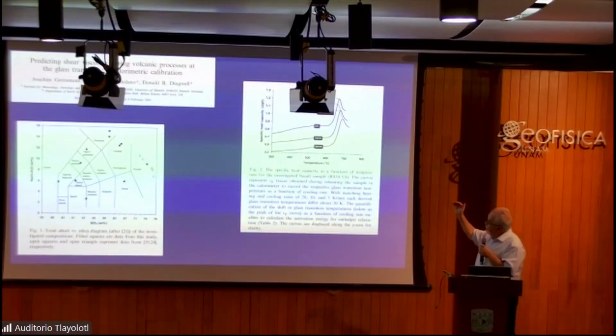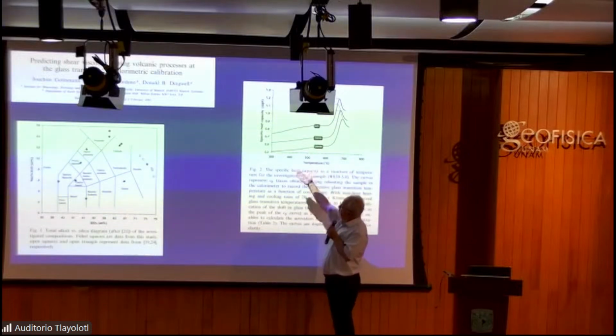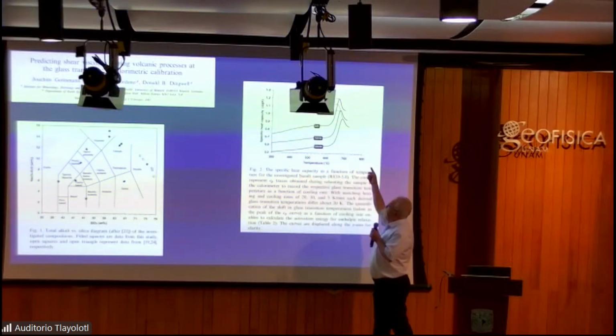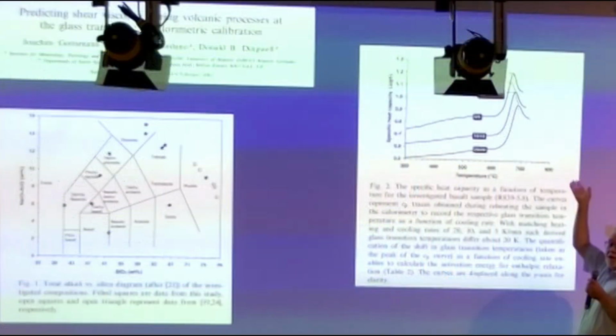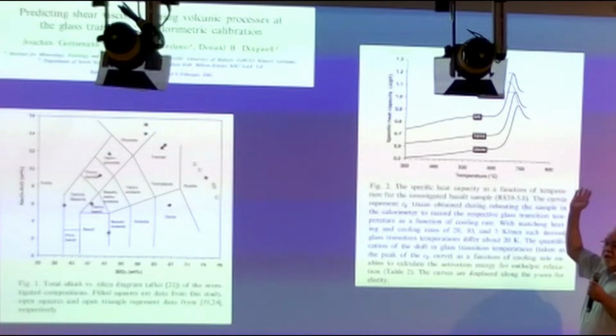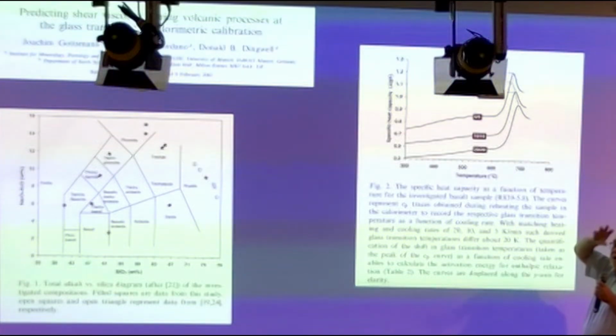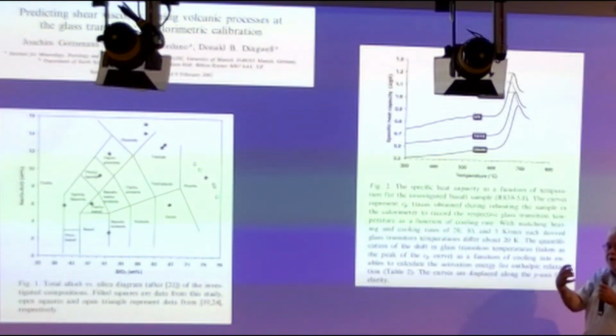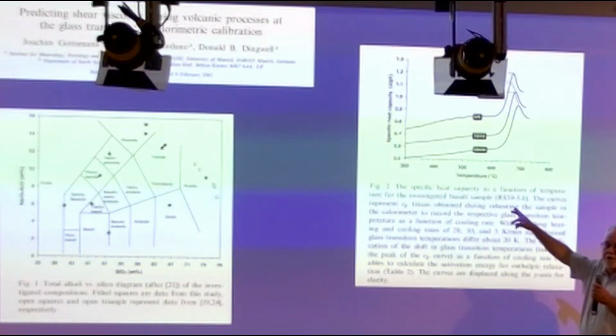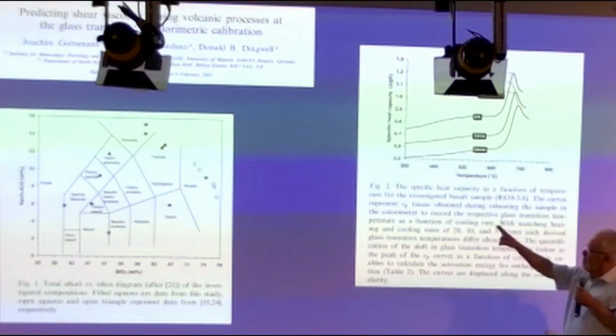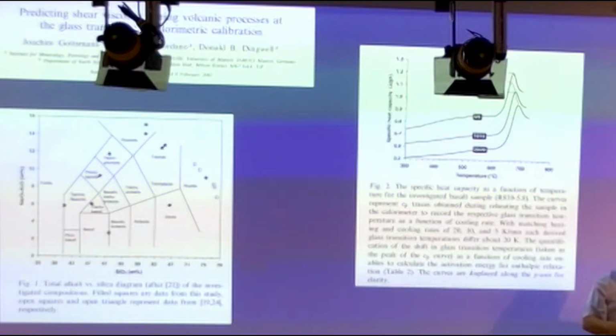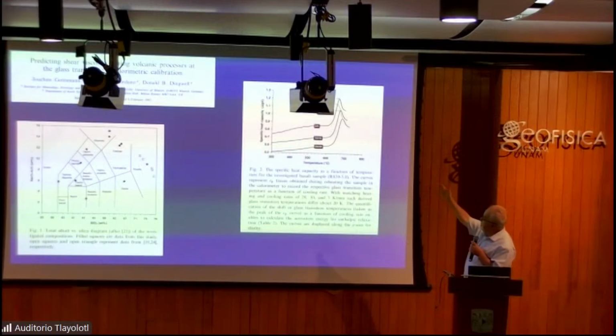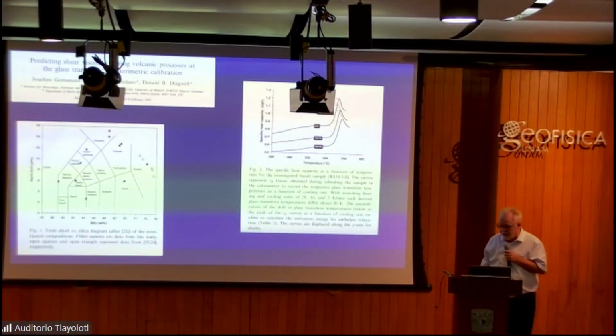And you have on the left-hand side a heat capacity which is relatively low at low temperature, and you have on the right-hand side the hint that the heat capacity is going to be much higher. And the reason it's much higher is because you have the liquid structure changing through configuration as it goes up in temperature, because the liquid has no lock on the structural state. The glass is frozen in its structural state, so it only has vibrational components to the heat capacity, but once you cross the glass transition, you have vibrational plus configurational. And that configurational change literally makes the difference between the left and right-hand side of the diagram. So the peak in the middle is what they call the glass transition in glass science.